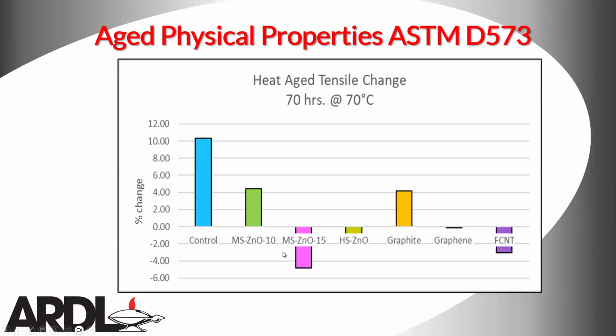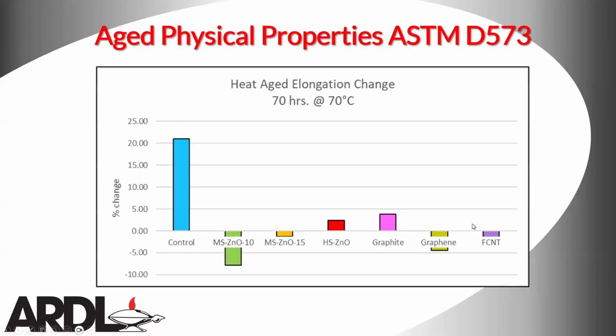But you can see that by adding a little bit of thermally conductive filler, you actually reduced your change in aged tensile properties by half. And this is all happening because you're dissipating heat, and it is improving your change after heat aging and making the compound more stable. And you actually see that your high surface area zinc oxide and your graphene had the least amount of change.